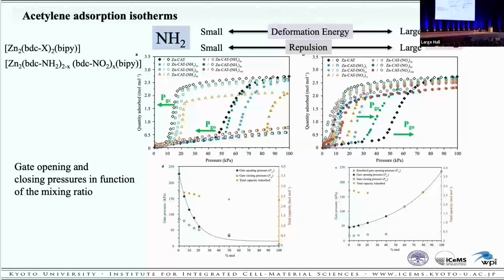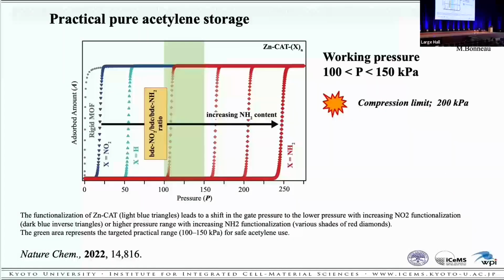Once again, as the nitro content increases, this pressure goes downward. On the other hand, in the amino case, it goes upward. This is the objective and the result of this study. By changing the mixing ratio of substituents, we succeeded in moving the temperature and pressure region where acetylene explodes, to obtain an effective adsorption isotherm.